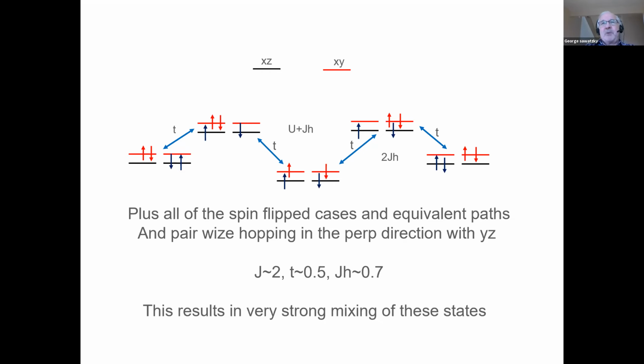And they claim in that paper that it has a hole pocket and an electron pocket, but the height of the pocket is only a few millivolts. So you have basically zero electrons, but you also have a gap, which is a superconducting gap, they claim, which is comparable to the Fermi energy in that particular case, meaning we're perhaps in trouble with BCS theory. But I don't know how reliable that is, especially the analysis of these backscattering experiments and the scanning tunneling experiment, how well you can actually predict the electronic structure to this kind of accuracy, I think is very difficult. Okay, thanks.